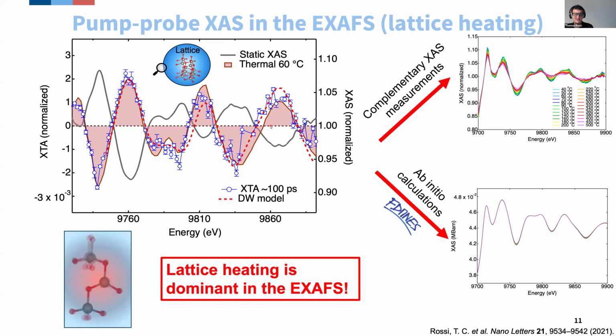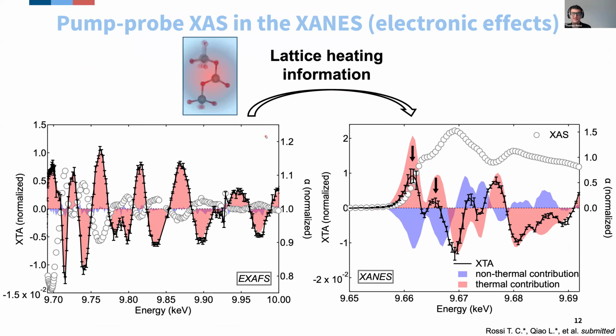Because if lattice heating is actually contributing a lot to the EXAFS, it's also contributing a lot to the XANES. And the way we highlight this is by using the information we have just extracted, that lattice heating is the dominant contribution to the EXAFS, and we report this information into the XANES. And what we can see is that when we compare the contribution from lattice heating, that's highlighted in red, and the pump probe data, that's the black line, we can see that there is a systematic difference now between these two curves in the XANES.